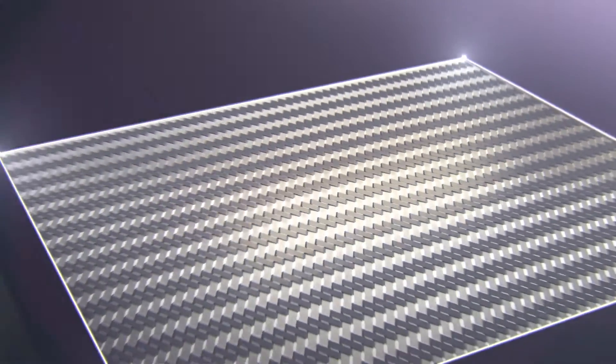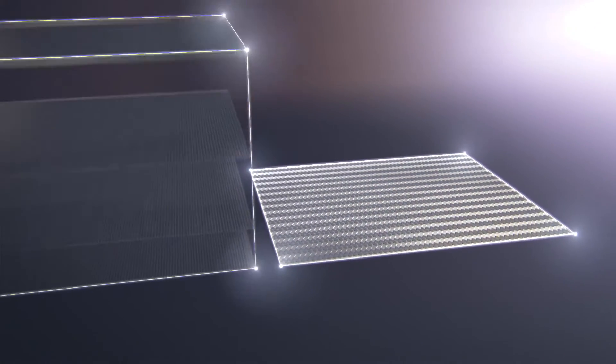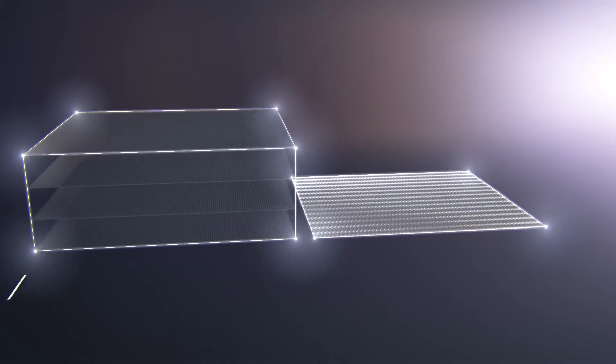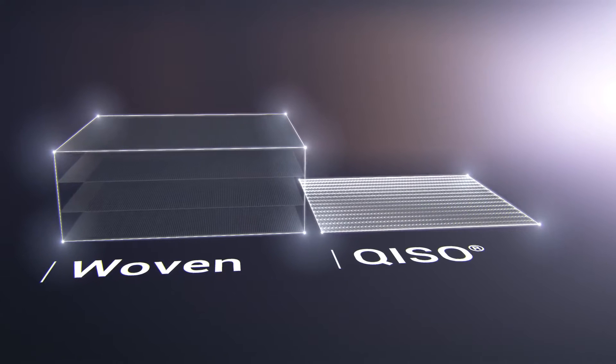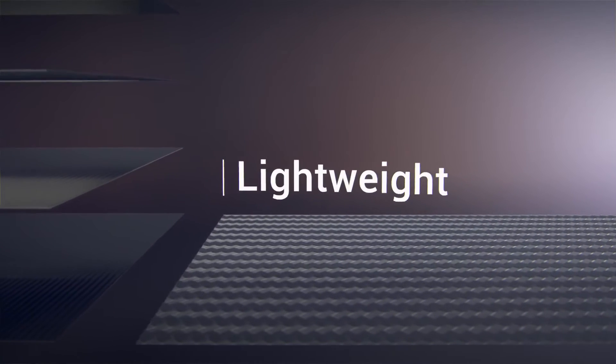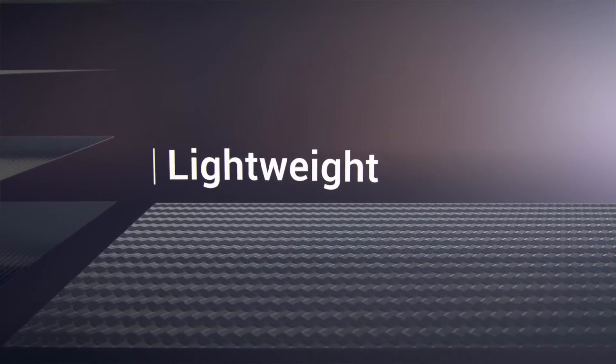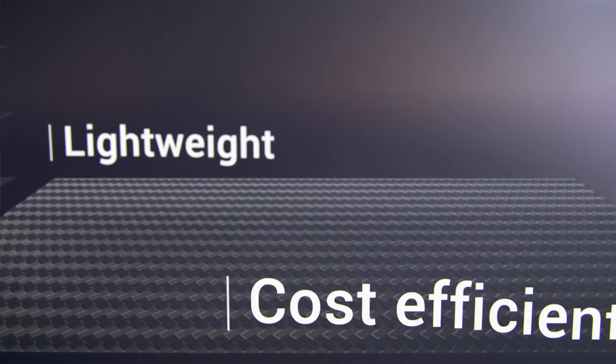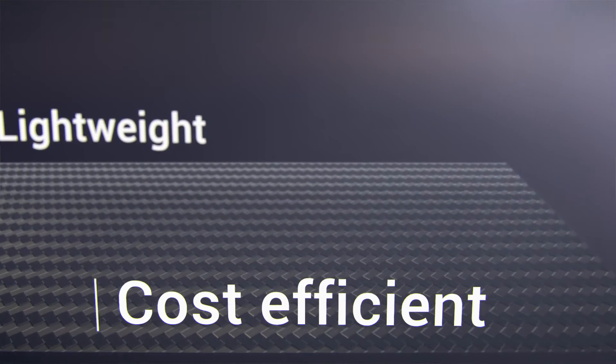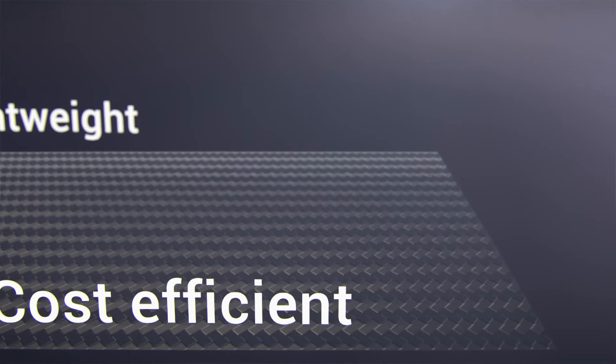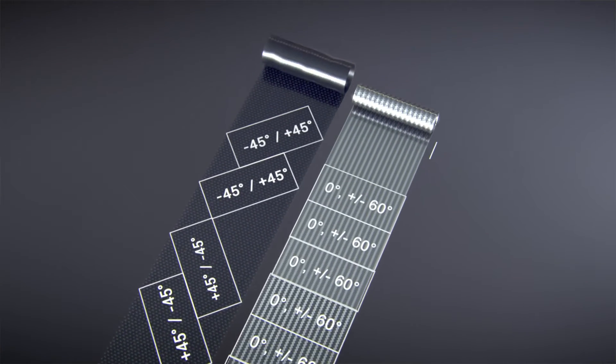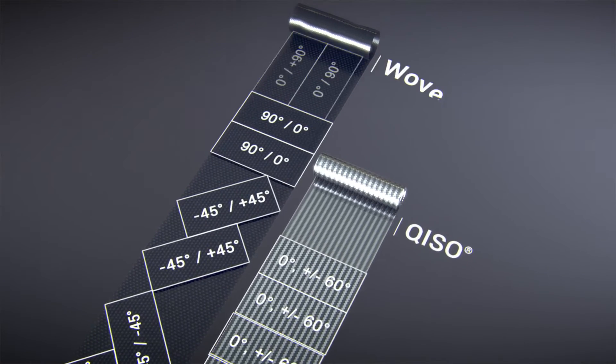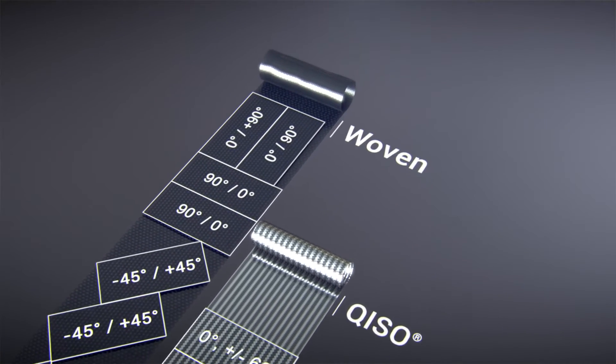Increments of four layers of woven fabric are required to achieve a balanced quasi-isotropic laminate. With QISO, the fabricator has the design flexibility to use the exact number of plies necessary to meet strength and stiffness requirements, minimizing part thickness and reducing material and labor costs. Cutting patterns of QISO fabric is straightforward. Rotational placement is not a concern.